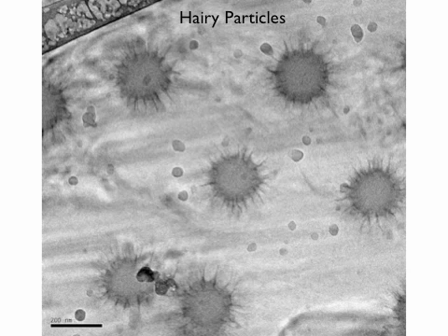And then you might say, oh, Stefan, you're talking nonsense, because the scale bar here says a bit less than 200 nanometers for the core, and if these are brushes, then I can see individual polymer brushes, which obviously would not be possible on this length scale, because one chain would be what, 0.1, 0.2 nanometer. Now the funny bit of this particular sample is the ice is really thin and it partially crystallized, and you can see that because you have these streaks in the ice.